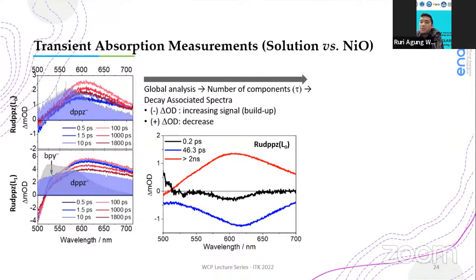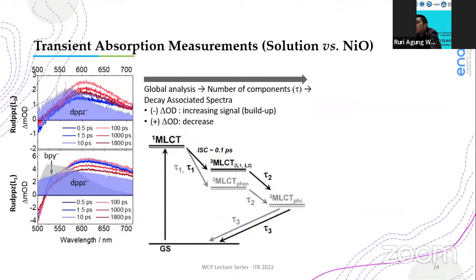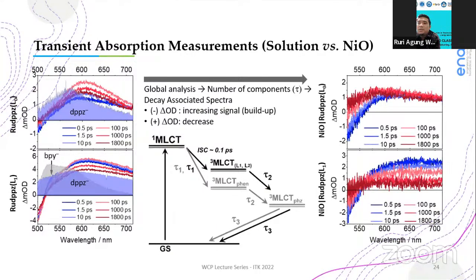So the excited state decay of all complexes can then be illustrated in the energy diagram as follows. The ground state absorption induces the first excitation to the singlet MLCT state, and then there is intersystem crossing, there is 3MLCT, and then it decays back to the ground state level. So now we look at the transient absorption spectra of the complex immobilized on nickel oxide. The transient absorption spectra here look different from those measured in solution. So this indicates at least the first interactions at the interface of the dye-sensitized nickel oxide.